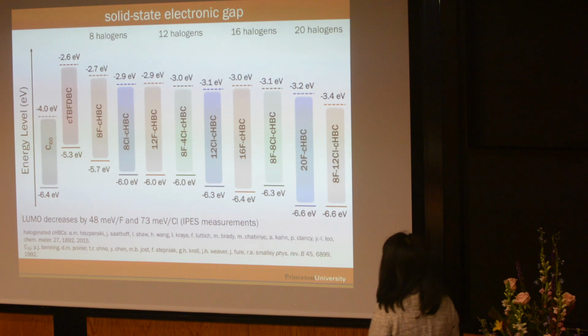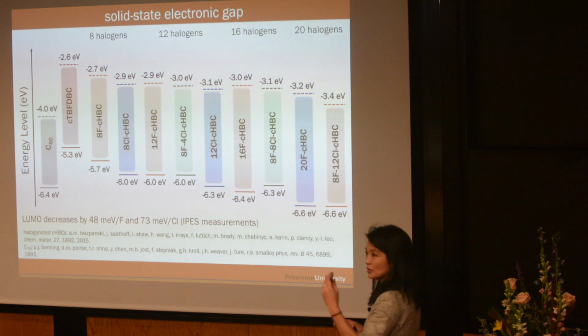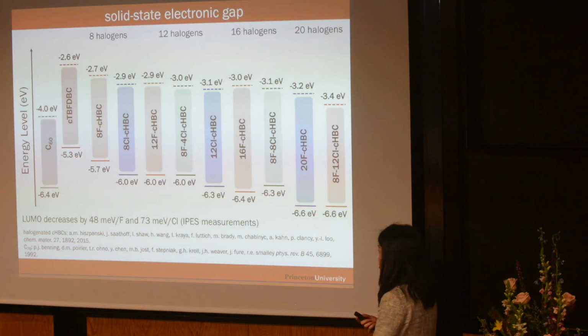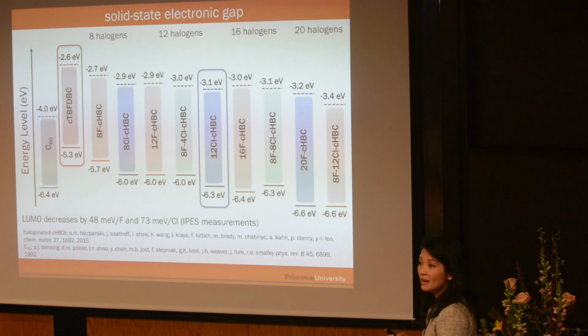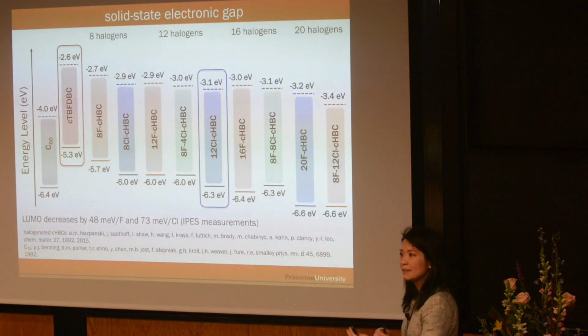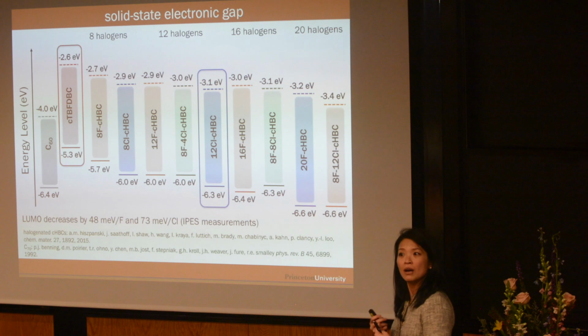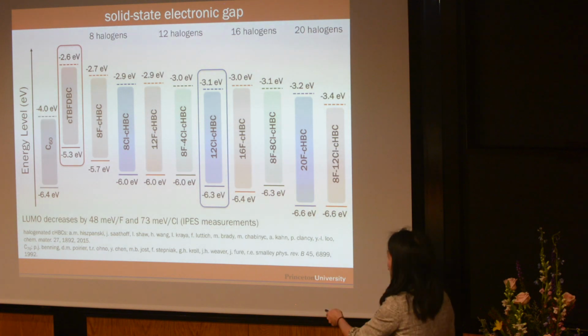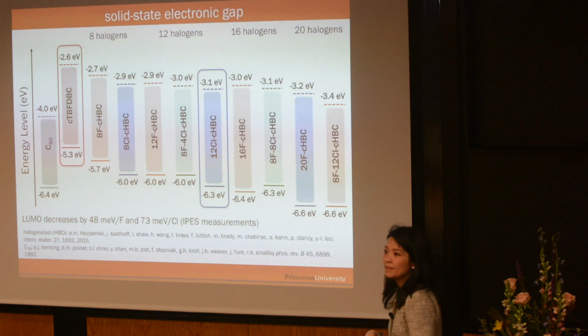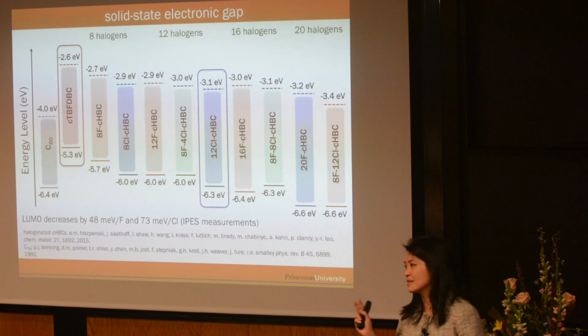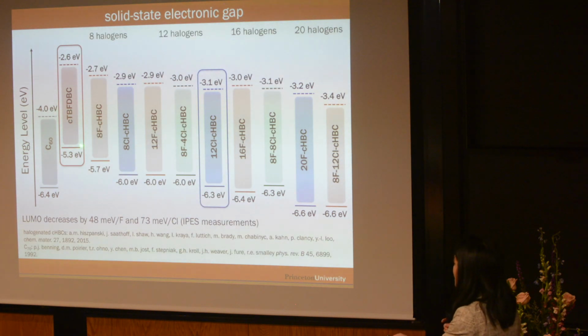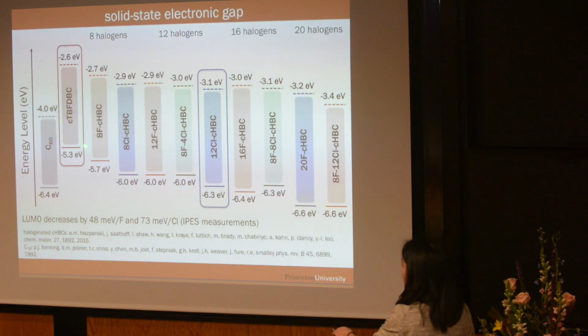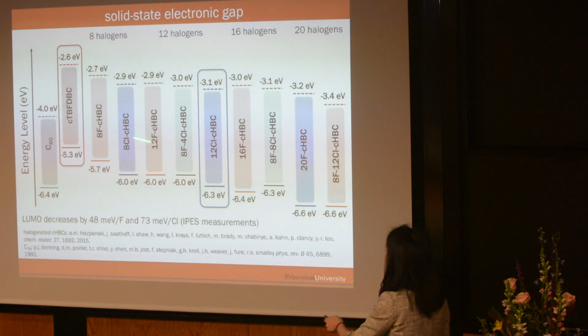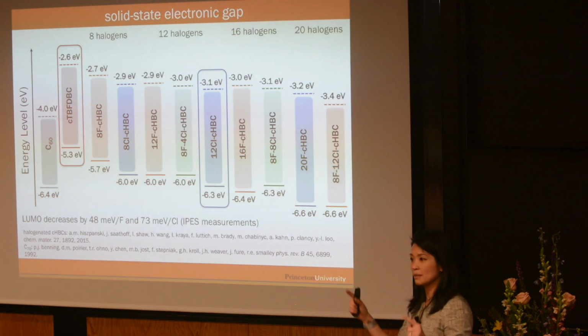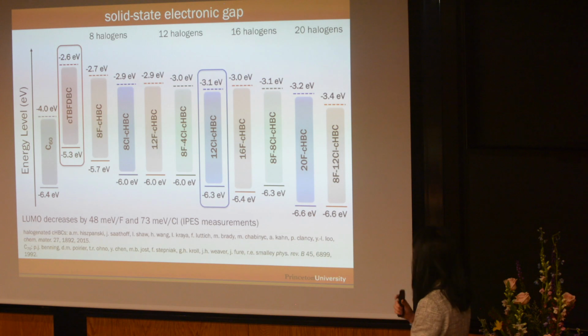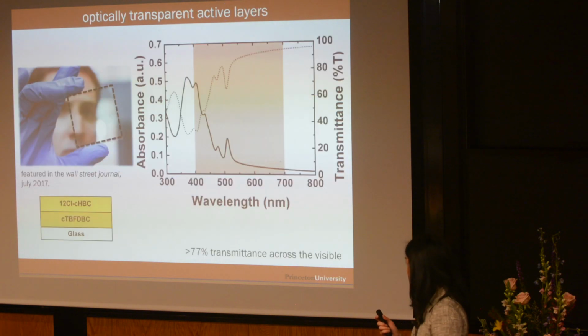So now we have a library of compounds, the donors that you saw earlier on, and the acceptors that I've shown you here. We can pair things together. We decided we need about 0.5 eV LUMO-LUMO offset, so we chose TBF with 12Cl. We've made a bunch of other pairs since, but let me show you data from TBF and 12Cl. So again, this is our donor, the benzofuran compound, and then 12 chlorines on the peripheral aromatic ring of a coronene core is our acceptor.